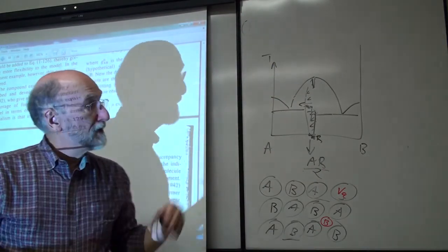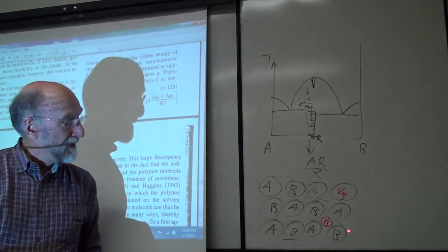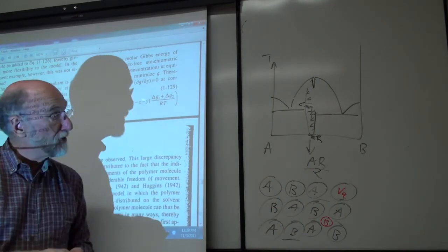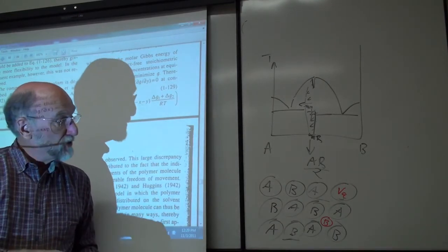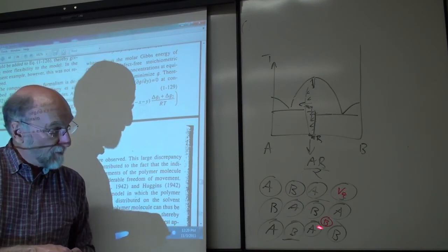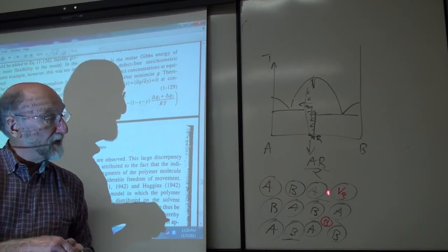Okay. Doesn't go to zero immediately, of course, but it rapidly decreases. Or if you go on the other side, the number of vacancies increases and the number of B's rapidly decrease. So these are called the majority defects. The majority defects in B-rich solution are interstitial B's. The majority defects on the left side are B-lattice vacancies.